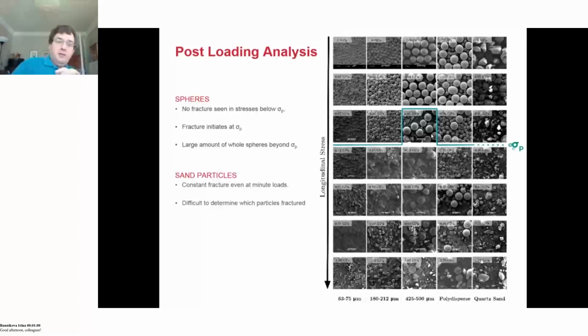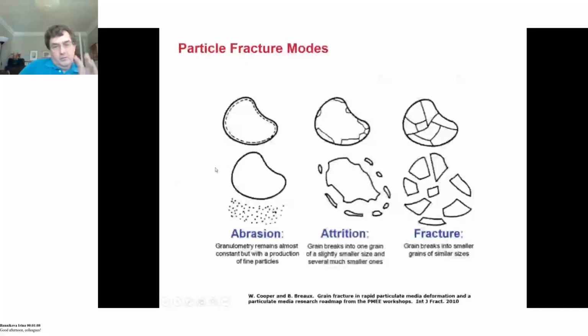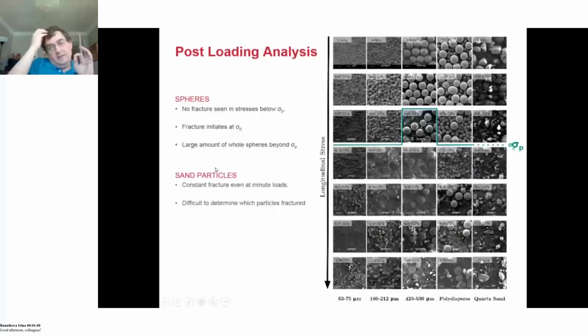So smaller grain size particles are stronger in terms of their initial mechanical response. However, because we're dealing with the same material, they will ultimately fracture, and in this range of conditions, they started fracturing at the same level. So how does that play? From this, we get the idea that with the glass spheres, we have a range of compaction behaviors, and we also know when particle fragmentation becomes important.